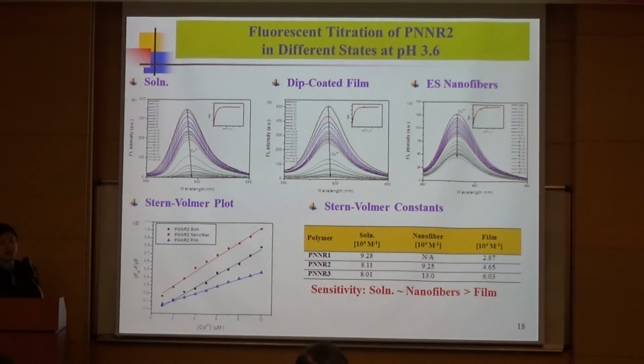However, again, the sensitivity was different among these three states. So in order to get a quantitative comparison, we constructed a Stern-Volmer plot. From this plot, we extract the Stern-Volmer constant from the slope, so we can quantitatively compare the sensitivity among these three different states. From this table, we can conclude that the sensitivity for the polymer in dilute solution and in nanofiber conformation are similar, and much larger than the sensitivity of the polymer in thin film conformation.